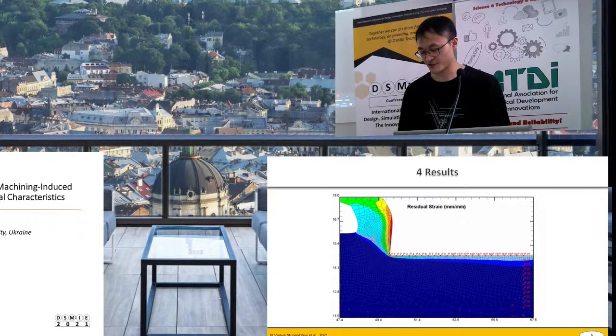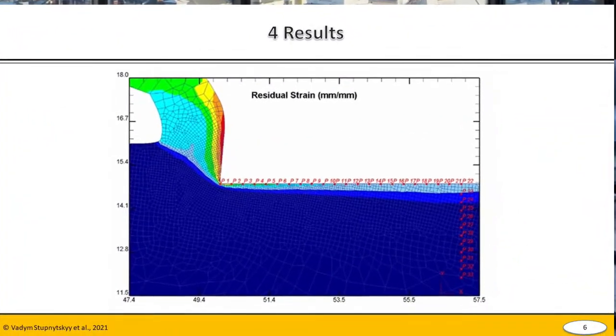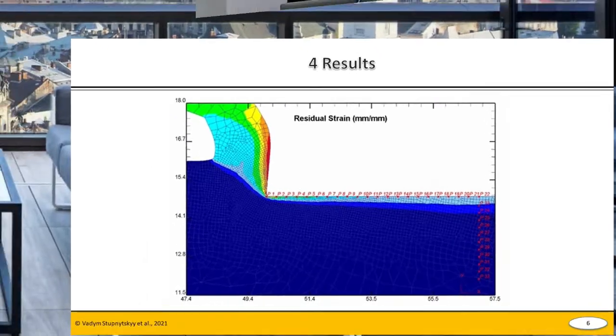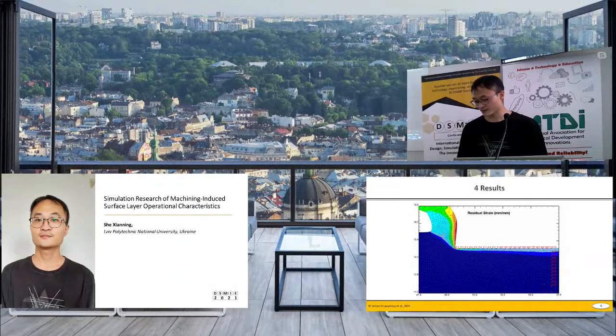Hardening of the machined surface layer is in most cases harmful and reduces the performance of machine parts. This is because after plastic deformation of the surface layer at room temperature, its specific volume increases and density decreases. This promotes faster diffusion processes at high temperature and accelerates the processes that reduce the resistance of the material to dynamic destruction. Prolonged exposure to high temperature on the hardened material quickly leads to its intensive softening, which reduces the overall performance of the parts.